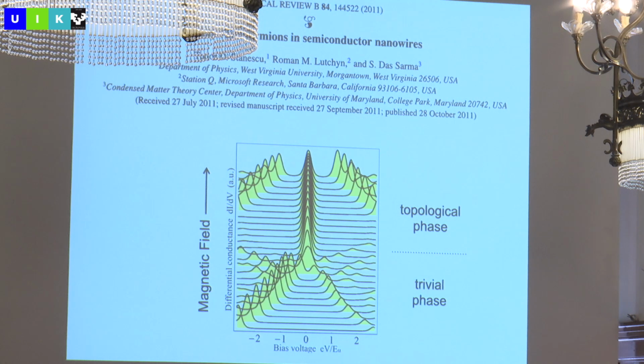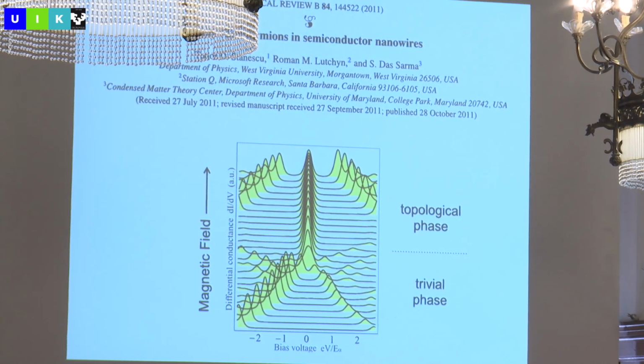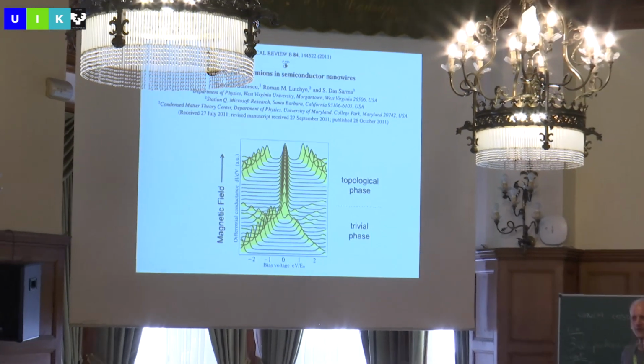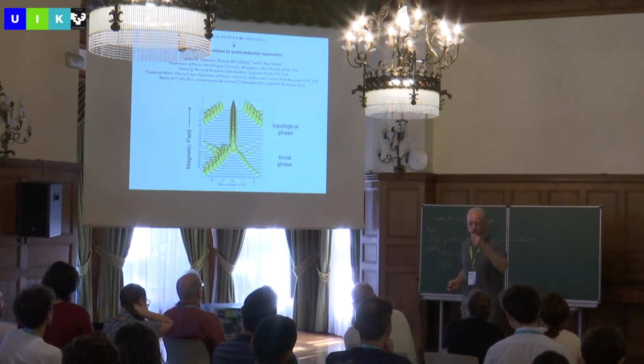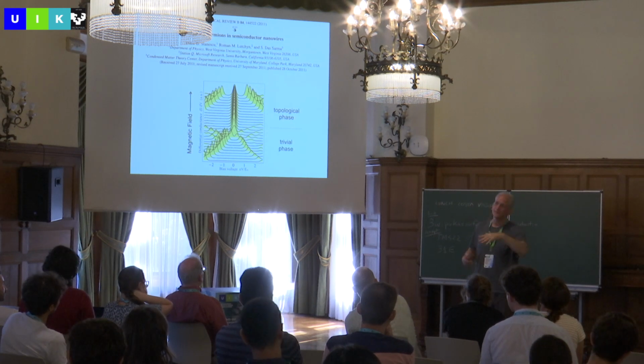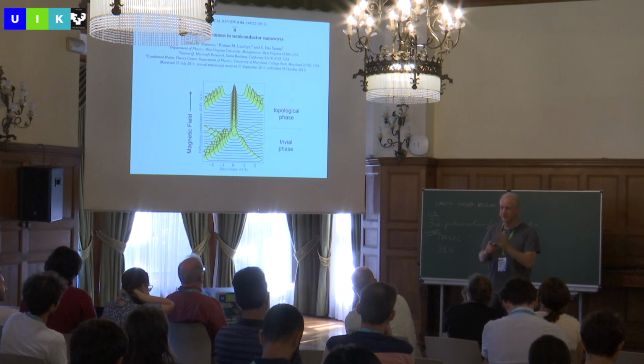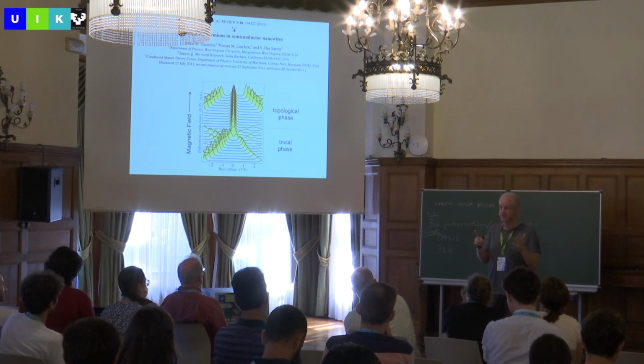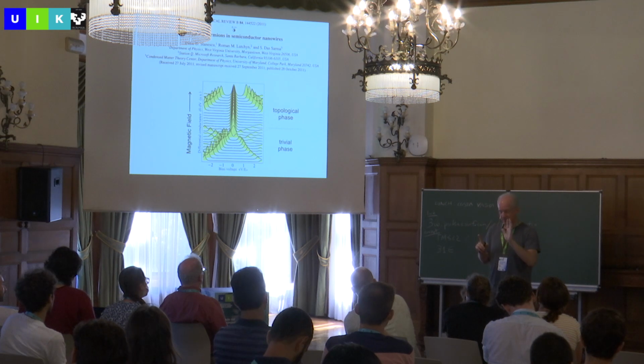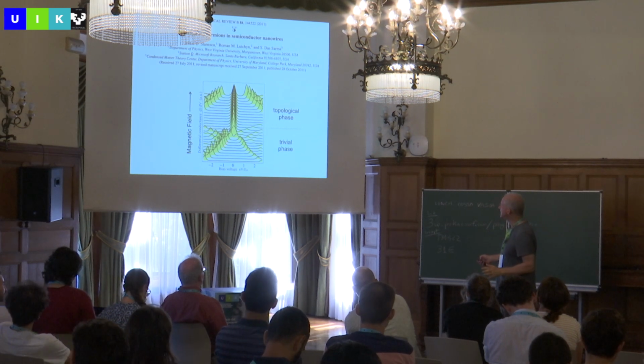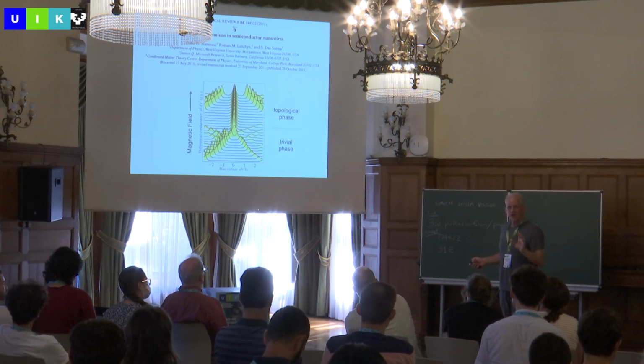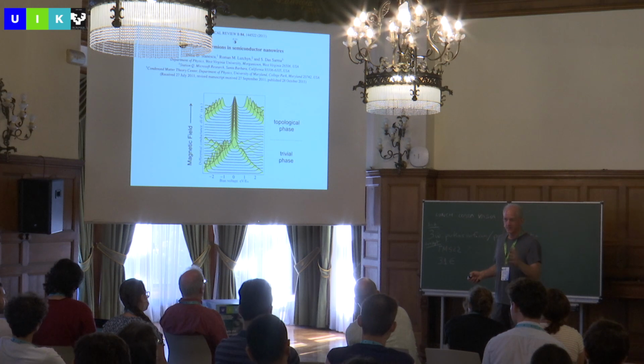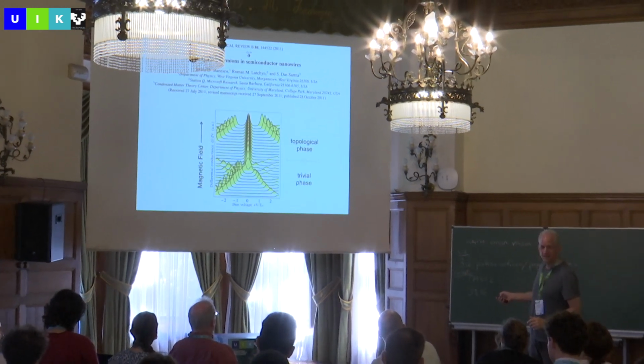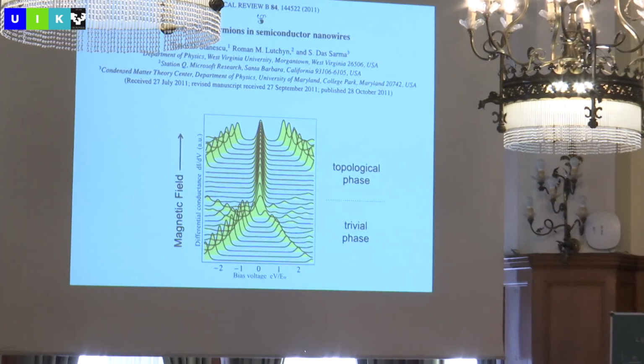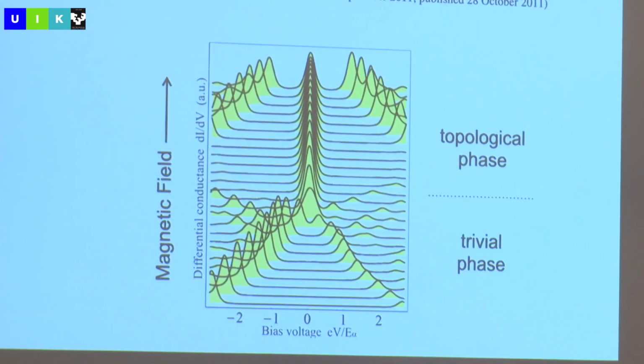the density of states. If you tunnel with weak tunneling into a superconductor, the tunneling conductance, the current that you inject at a certain voltage, will reflect the density of states. Like Fermi's golden rule, it's proportional to the density of states. If the tunneling is not weak, then there's all kinds of other more complicated things. In fact, there's an enhanced conductance in it. But at weak tunneling, you measure the density of states. So if you weakly tunnel in, this is now, the previous graph was a density of states calculation. This is an advance because this is a conductance calculation. Now we're getting pretty close to what somebody in the lab could actually think about with a voltmeter trying to measure.